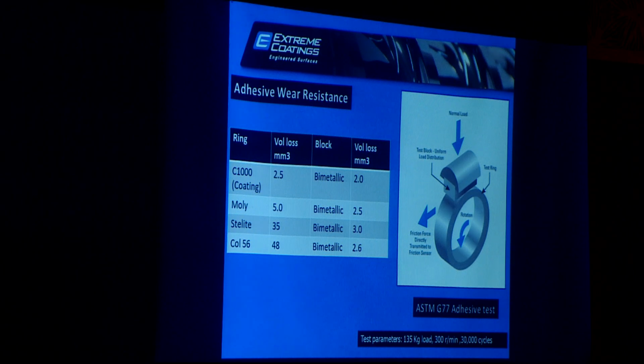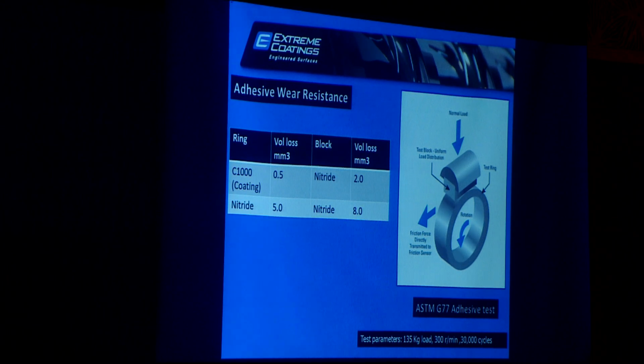The same thing applies to adhesion also. A question may come: if we improve so many properties of my steel, is it not going to affect my barrel? No, it does not. That's the beauty of the solution. The reason is tungsten carbide, molybdenum, vanadium are elements which have a very high melting point. When two surfaces come in contact with each other, because of the higher shear, in the nitrided case it used to create a weld which used to rupture the surface. But in this case, welding is not going to happen. The screw is going to slip on the barrel surface, and because of that, this coated screw even complements the nitrided barrel life also. That's the beauty of the solution. These are all comparisons with different steels, and what the results were.